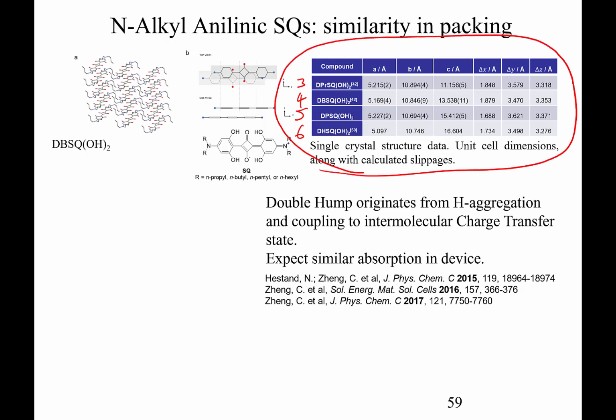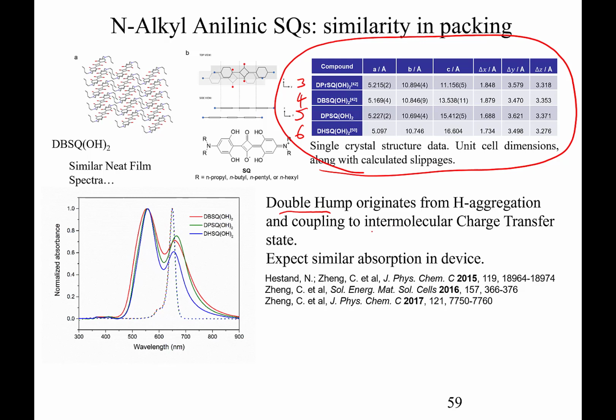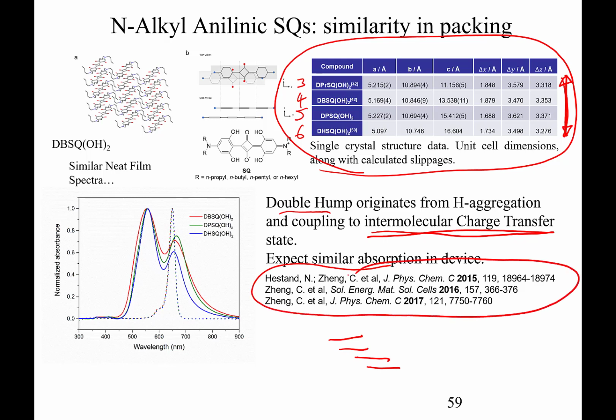structure. And we've also recognized this double hump originates from aggregation, but that aggregation is coupled to an intermolecular charge transfer state. Why? Basically, the molecules are about 3.3 angstroms apart from each other, so they stack on top of each other like this, and that's close enough for a charge transfer process. And again, that's described in some of the papers that have come out from my group in recent years. Very much in collaboration and very much driven by the expertise of Frank Spano at Temple University.